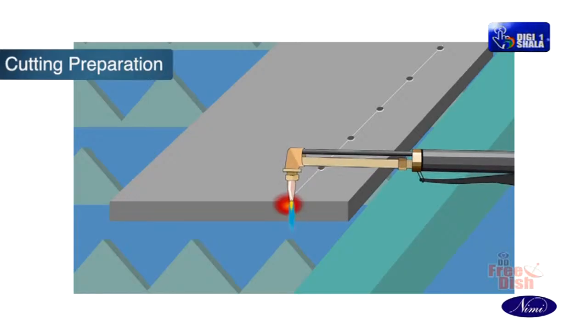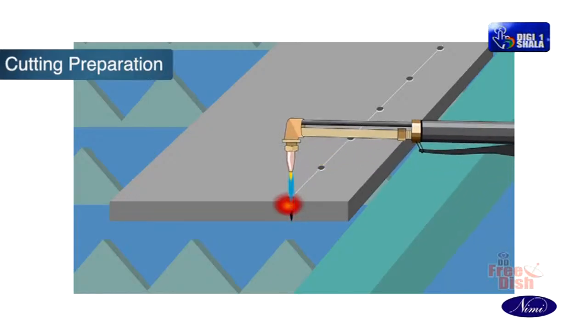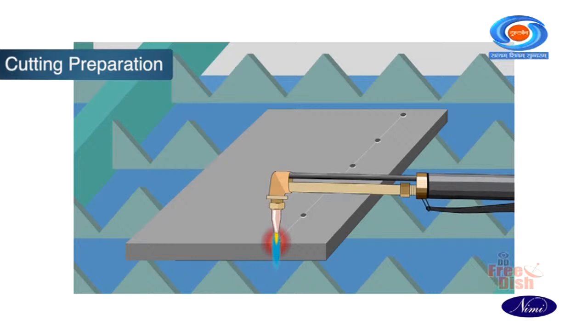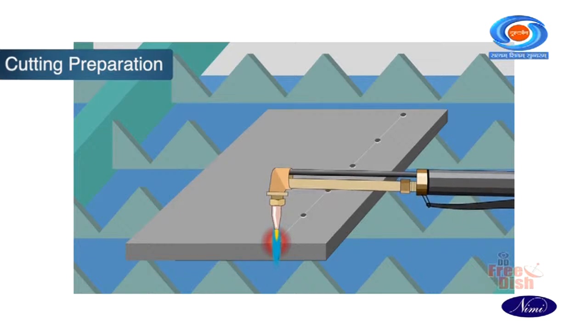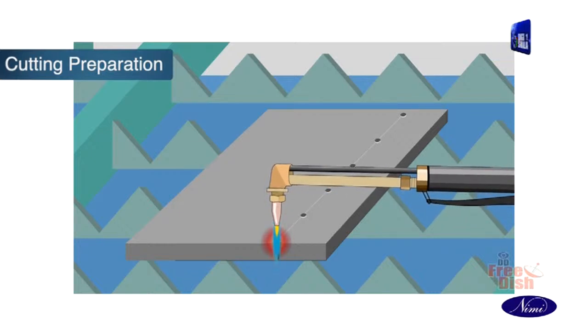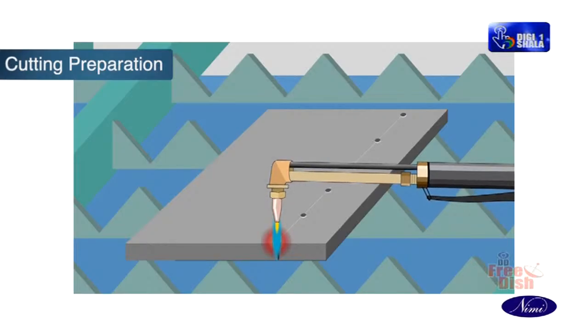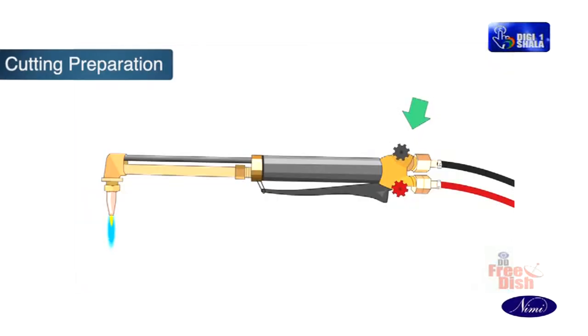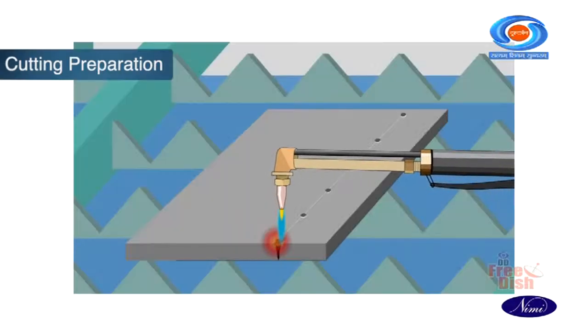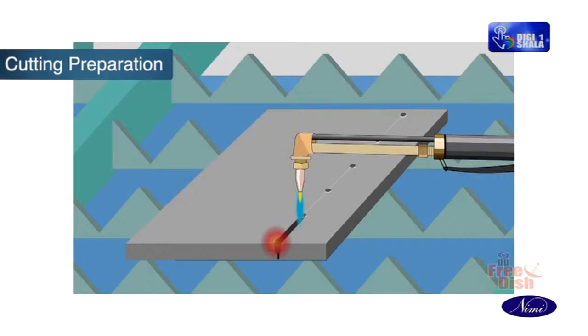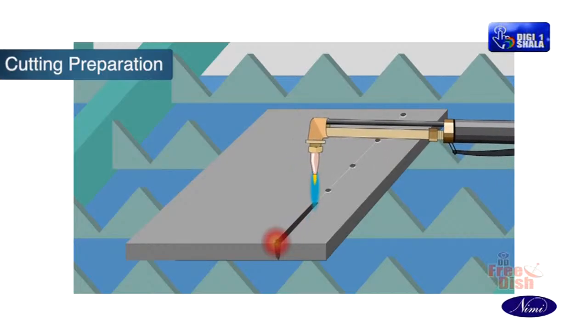Begin moving the torch along the line to cut. A short backward movement before the cut is carried out to clear the slag from the kerf. Release the extra oxygen, observe the cutting action, and start traveling along the punched line at a uniform speed.